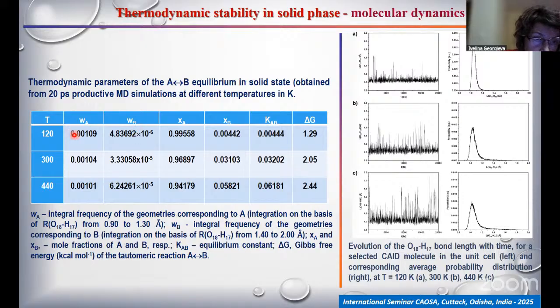So we can see that this value, which we can also consider the mole fraction of A and B, in solid state, the mole fraction of A is larger as compared to B, and we have calculated the equilibrium constant and Gibbs free energy for the tautomeric reaction of AB conversion. In this figure, we can see the evolution. This is from dynamics calculation results. Evolution of the OH bond length. This is where the hydrogen is mobile.